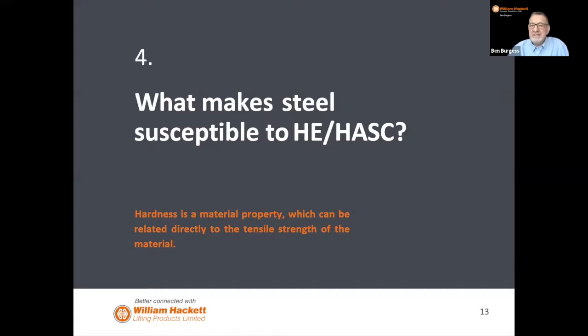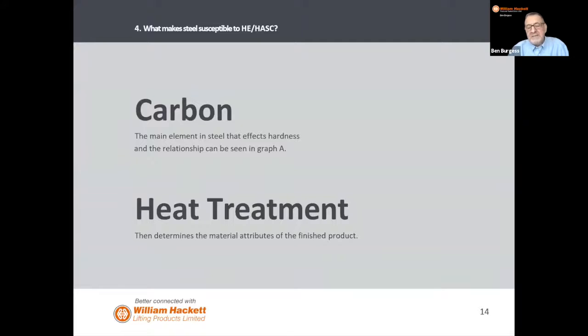So the harder the steel, the more susceptible it is to hydrogen embrittlement and therefore to hydrogen-assisted stress cracking as a result of that. Now, there are other factors that contribute to the hardness of a steel, but the simplest is the carbon. The carbon content is a simple and cheap and effective way of making a steel extremely hard and giving it a high working load limit, which perhaps onshore, when there's no dynamic load amplification or anything going on, is perfectly suitable. But offshore, it comes with risks and is less than ideal.